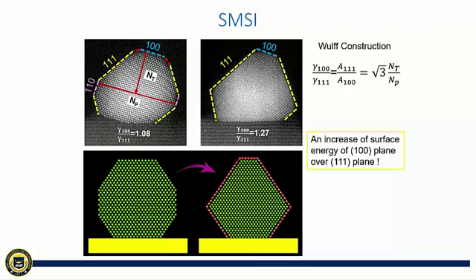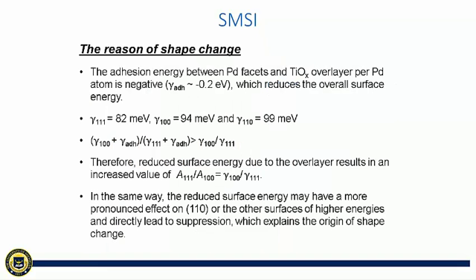And here we use the Wulff construction. The Wulff construction can correlate the surface energy ratio between two facets with the area ratio of two facets. The lower the surface energy, the bigger the area it will have in the particle. And also, it is proportional to NT over NP. NT is the number of atomic columns from the 100 surface to the diameter, and NP is the number of atomic rows in the diameter. So here we can see the surface energy of 100 over 111 increased from 1.08 to 1.27. So this indicates that the surface energy of 111 has relatively lowered. It becomes energetically more stable than 100. So what is the reason?